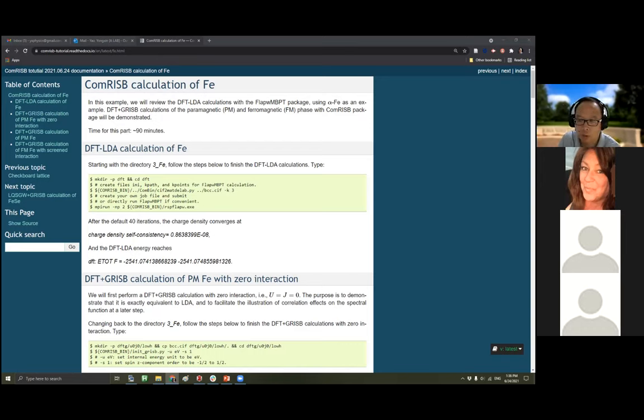I mean, there is this famous Hund's transition, which I think is closely related to the iron pnictides. If you fix U over J and then scan U, there are two regions of reduction of the Gutzwiller quasiparticle weight. Initially it reduces really fast, then it tends to saturate. That's what people often call the Hund's metal phase. But again, the answer is that generally we don't have this kind of limitation on the upper limit of U over J.